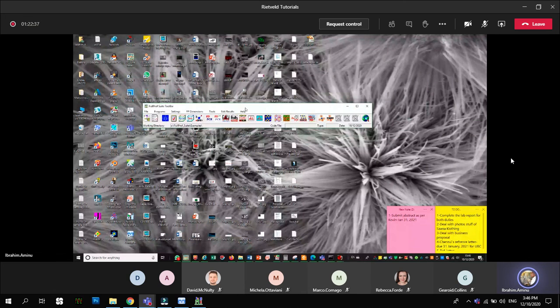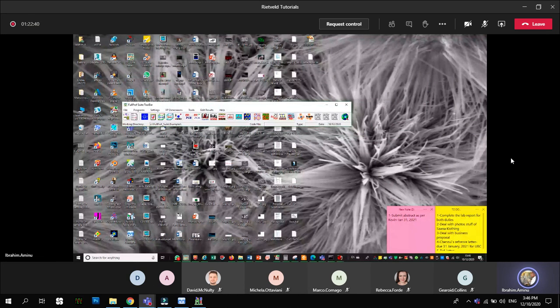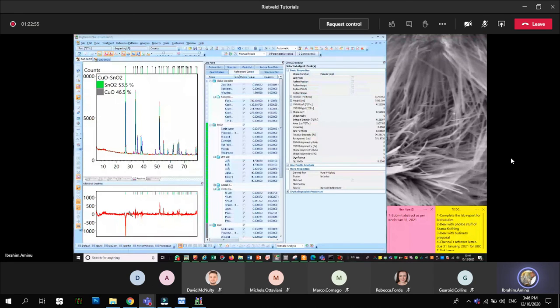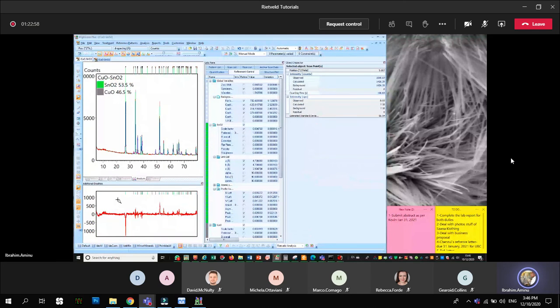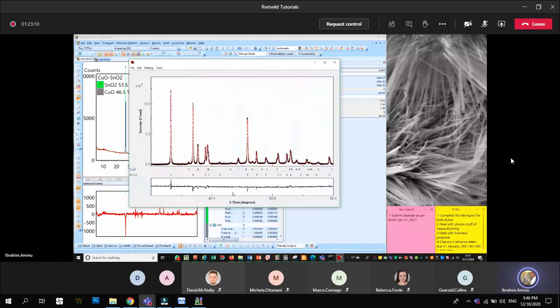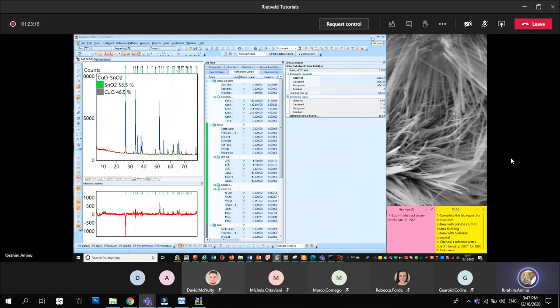And sometimes if it's not fitting well, for example, you see here we have the difference profile. We have this long sharp peak and this, which are all indication of not being a good fit here and here. But if we go to here, we can see it's much better here compared to here. So depending on the material you are fitting, then you may decide the software that will give you better looking results that you can really publish. So I think that is it for now.